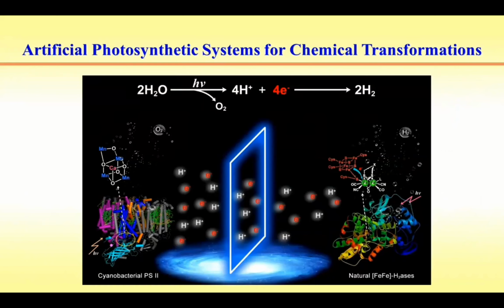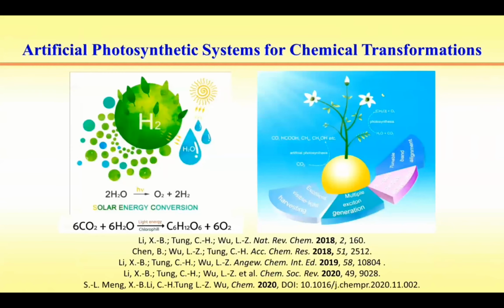At the same time, we also mimic the oxygen evolution catalyst in nature to deliver oxygen from water. In this case, we construct this integrated system to split water into oxygen, with the protons and the electrons delivered to the other active site for hydrogen evolution. Following this kind of picture, we have achieved water splitting into hydrogen and oxygen.